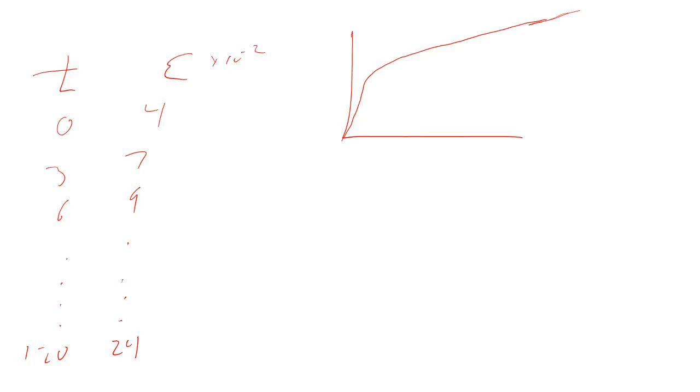If I were to drop this down and start decreasing with the same curve, I would decrease, but once I'm asymptotically in the region where the slope is constant, I would just go out at a plastic, because I would have the same slope. So this needs to decay. That means you need to either assume that it decays in some way, or think of a really simple functional form.